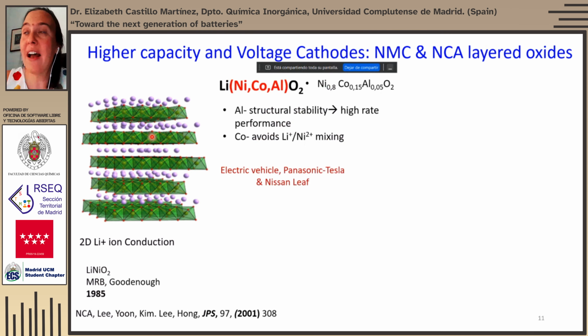However, they have a high reactivity towards the electrolyte and also high thermal reactivity. So strategies involving doping, such as cobalt that avoids lithium-nickel mixing that occurs in the pure composition, or doping with some electrochemically inactive elements such as aluminum 3+, allow us to have materials with high rate capability. Actually, this composition is used in many commercial batteries, and you will hear of it as NCA.